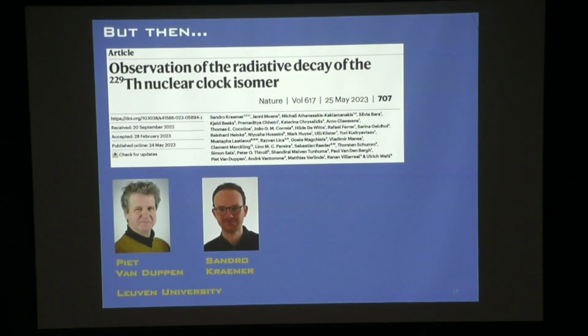And then last year, something really important happened. Piet Van Duppen at Leuven University did a crazy experiment. This was so crazy, I know people in the field who turned down being a part of the collaboration, but it totally worked. It's the best kind of experiment. And what he did was take like calcium fluoride or magnesium fluoride, some high band gap optical material, and at CERN, in the ISOLDE facility, implanted thorium-229 into them.